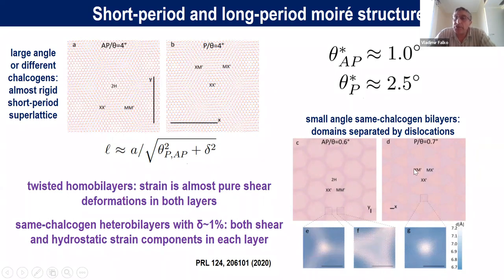For the parallel orientation of the unit cells, the structure is different. It's a triangular lattice with domains of MX and XM stacking. The lattice structures of these domains are mirror images of each other. And these domains are separated by domain walls, which are nothing but partial dislocations, known in 3R structure of bulk TMDs. And in the corners of the domain wall network, we have small areas, kind of dot-like objects, with XX prime stacking, which is energetically least favorable.